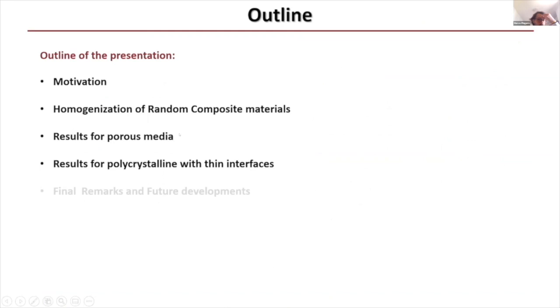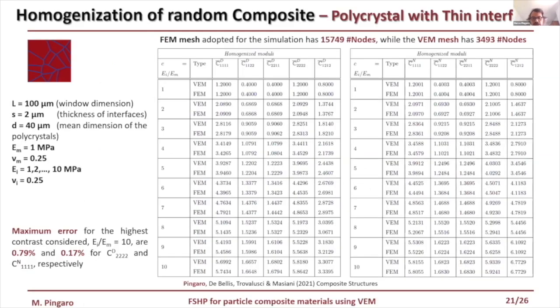Now I switch to the polycrystalline. So I want to present some initial results obtained applying the statistical homogenization to polycrystalline material with thin interfaces. The first result is a comparison between the proposed procedure using VEM and the standard procedure with FEM, assuming FEM as a reference solution.